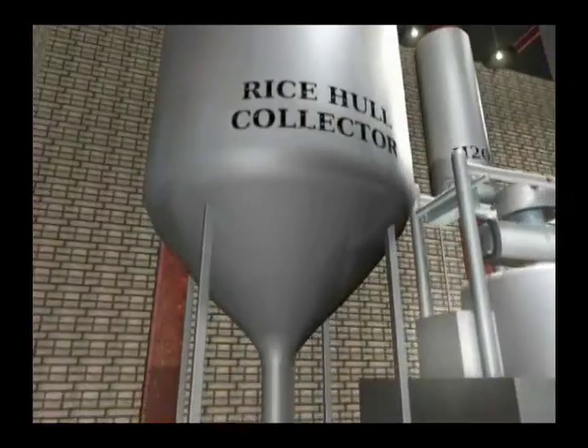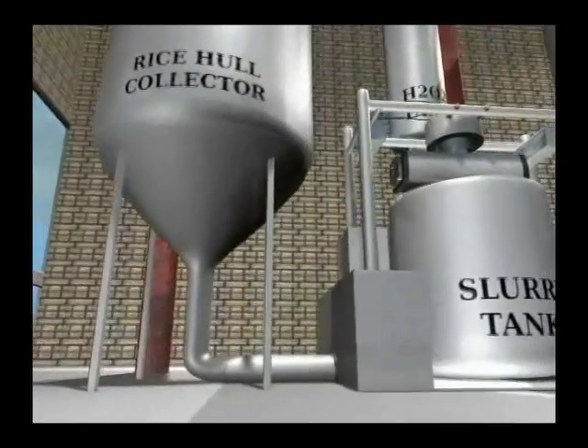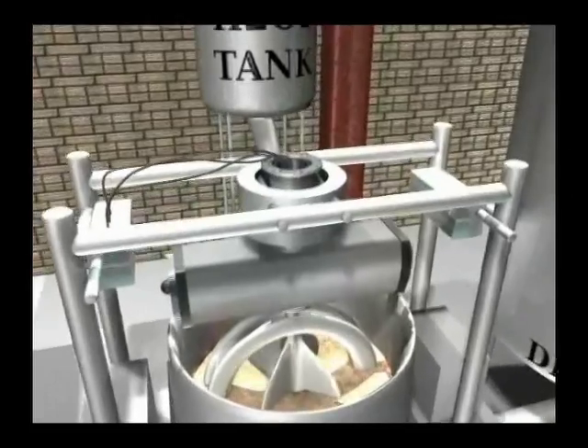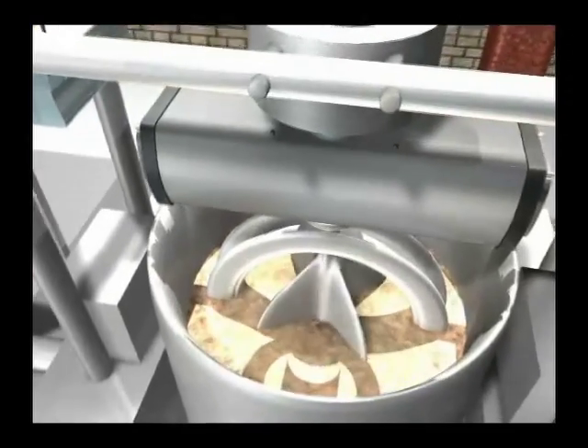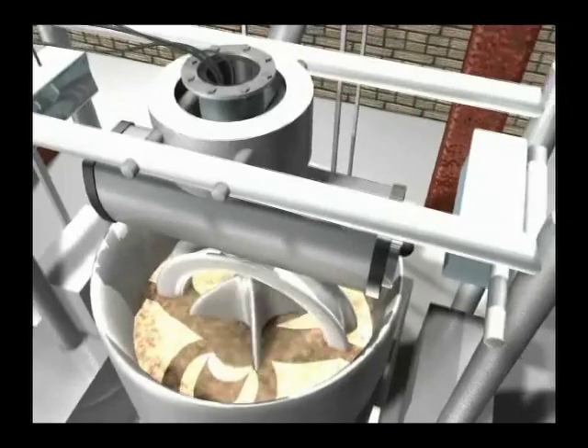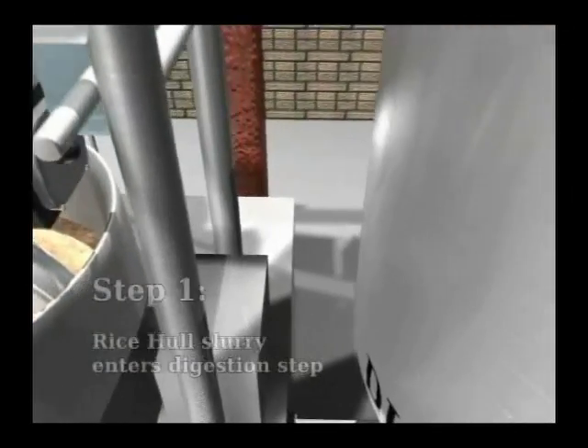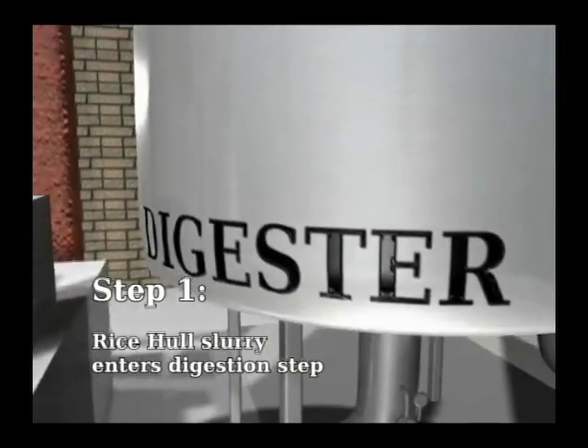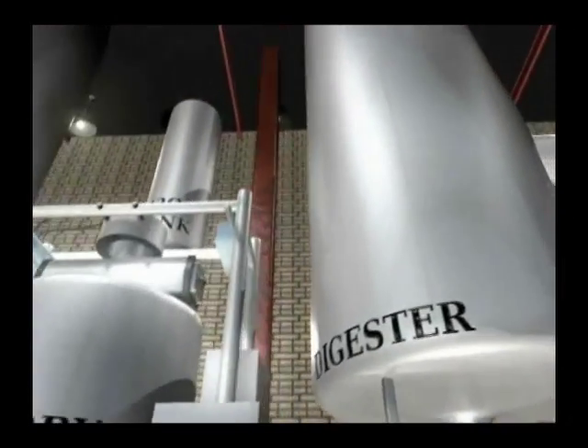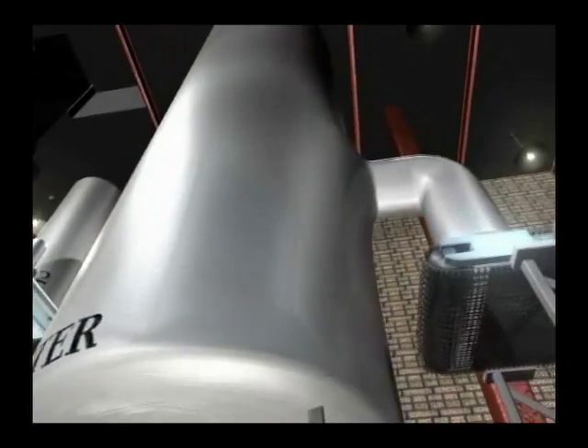And thinking about why the carbon wasn't burning away, it seemed likely that it was because the lignin and cellulose in the hull were very long chain polymers, and the longer the polymer chain, the more difficult it is to have a clean burn. So we thought about how we would shorten that, and one approach was to treat in a slurry with hydrogen peroxide. Hydrogen peroxide would go in and essentially act like chemical scissors to shorten the polymer chains, and we took that approach, re-dried the hulls, and when we burned them on the bench, we got a nice white powder.